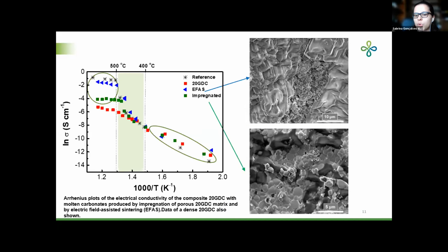So the samples produced by electric field assisted sintering, in blue, showed a higher conductivity than the samples obtained by infiltration, as we can see here. And we do not have the permeation results yet for the membranes produced by this method, but the conductivity results allow us to expect good values.